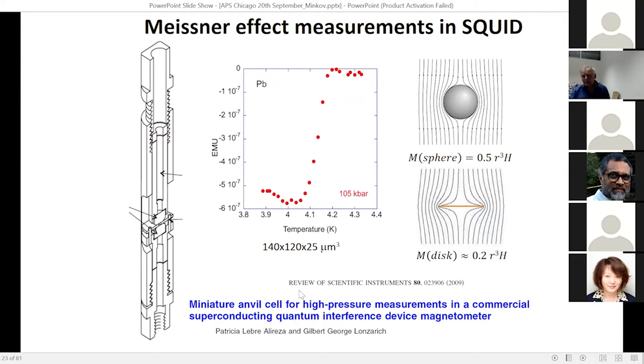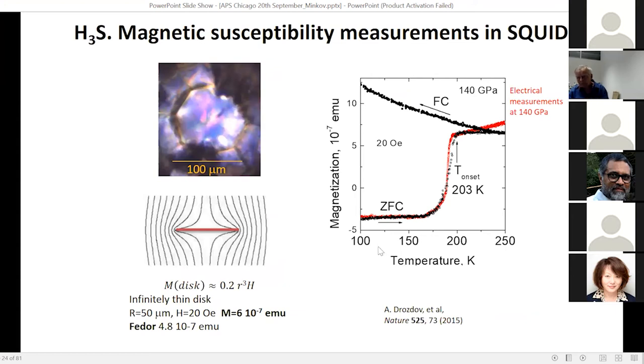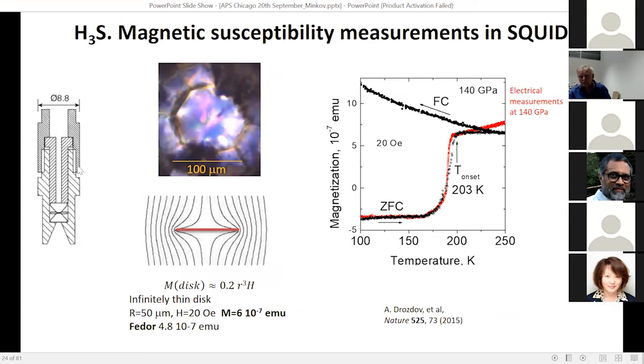So we have superconductivity, zero resistance, and the isotope effect. The next step was to demonstrate superconductivity not only electrically but also with direct magnetic measurements — magnetic susceptibility — which can be done with a SQUID. Before this work, SQUID measurements had been developed only up to about 20 GPa, and we needed roughly ten times more pressure. This was a really tough problem.